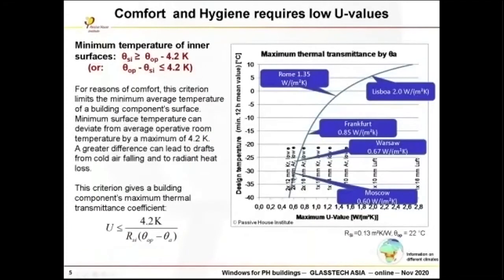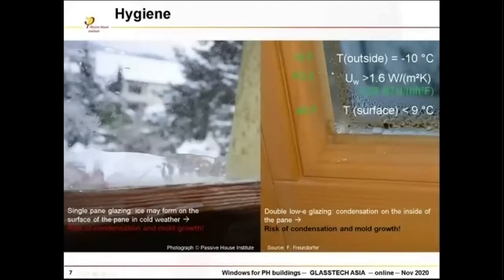If you now go into some detail with the requirements, you see that for very cold cities with cold winter temperatures, for example Moscow, you have to go down to about 0.6 watt per square meter Kelvin, the U value. Otherwise, thermal comfort will not be good enough for windows. The same is true for hygiene. If the surface temperature is too cold, you will probably get condensation inside of the glass and the frame, and this is not healthy, and may lead to mold growth and so on. So please help to avoid it wherever you can.